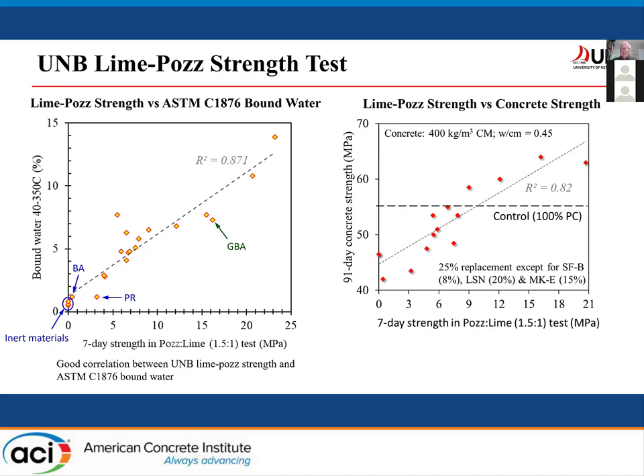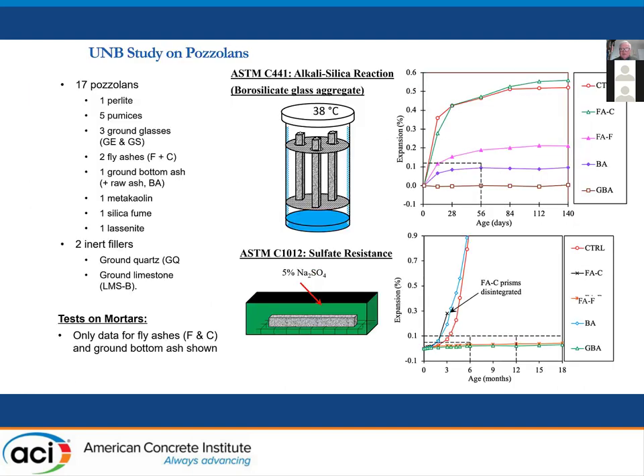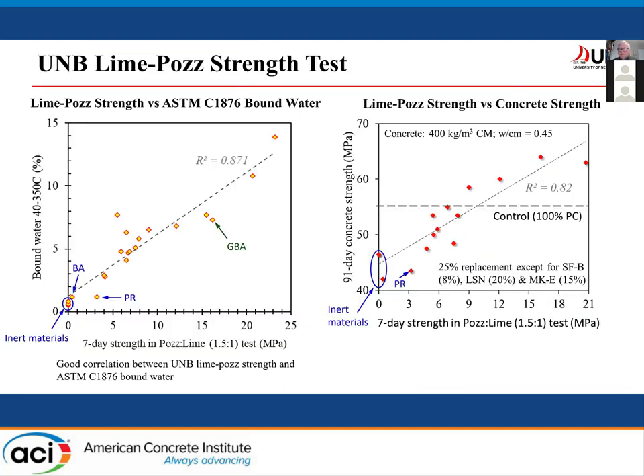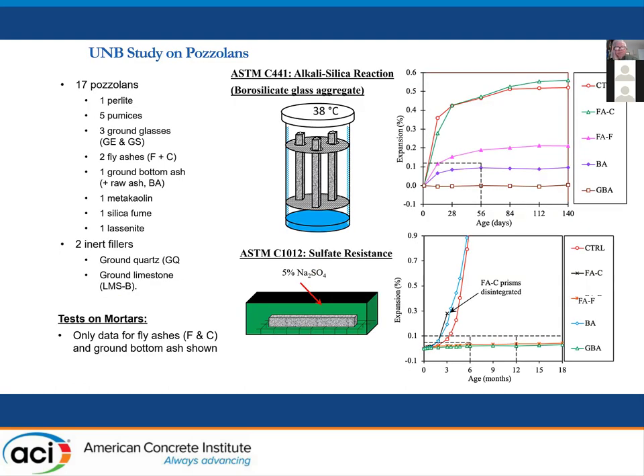And this is the 91-day concrete strength versus the 7-day lime pozzolan test. And again, it shows that good relationship. Again, there's the inert materials. ASR testing using the borosilicate glass or Pyrex glass test, ASTM 441, shows the reduction you get from the ground bottom ash, which is that bottom line there.